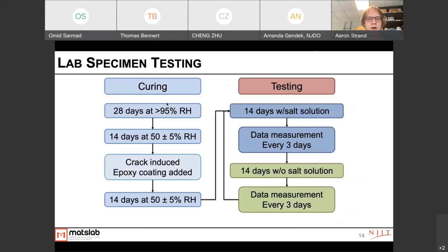So for curing, all our specimens were cured for 28 days in high relative humidity. They were then cured at 50% relative humidity for 14 days before the crack was induced and the epoxy coating was added. And they were cured for another 14 days at 50% relative humidity before any of the chloride brine testing was started. The testing involved 14 days with a salt solution on the top of it. And unlike in ASTM G109, where the data was only collected during the wet cycle, we collected data measurements every 3 days. Then the salt solution was vacuumed off for 14 days, and again we took data measurements every 3 days. Obviously 3 doesn't go into 14, so there's a 2-day interval between the last 2 measurements. And then this cycle was repeated continuously until testing was stopped.